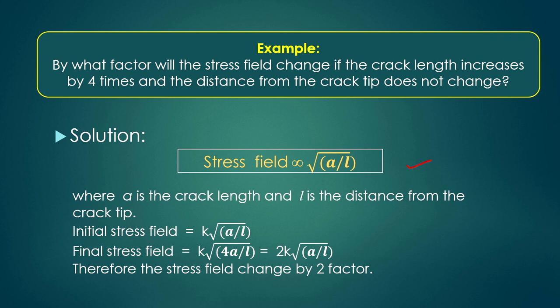Now, the initial stress applied as per the problem will be equal to K into root over A by L, where K is the proportionality constant, and the final stress will then be K into root over 4A by L. That means the crack length will be 4 times the initial length, whereas the distance from the crack tip will not change. So L will remain the same. So it will come as 2 into K root over A by L. Therefore, the stress field changes by a factor of 2. So this is a simple problem by which you can easily understand that the energy required is proportional to the stress field.